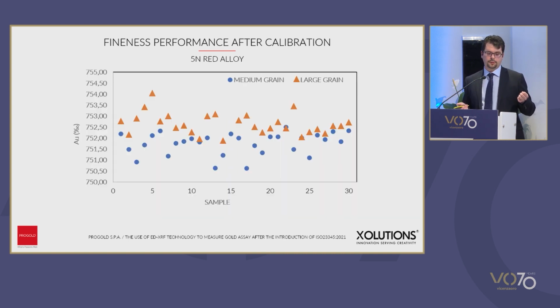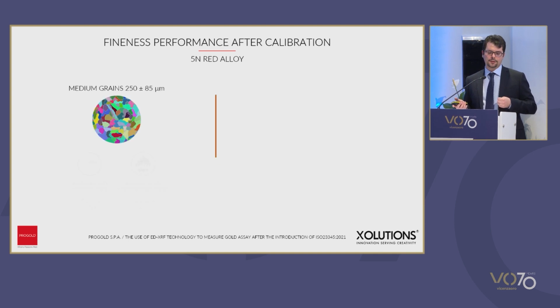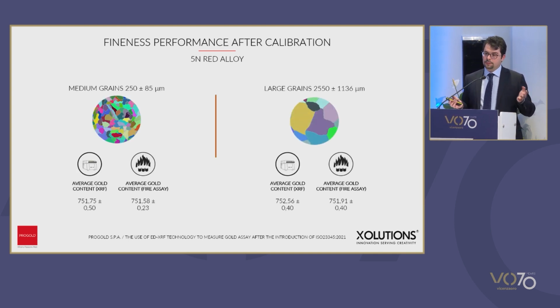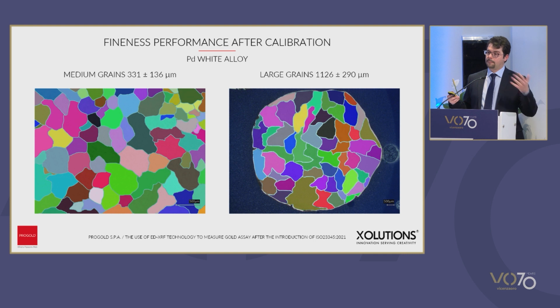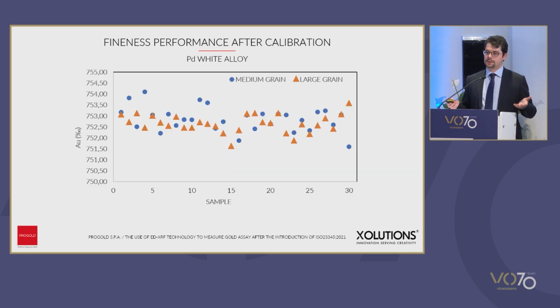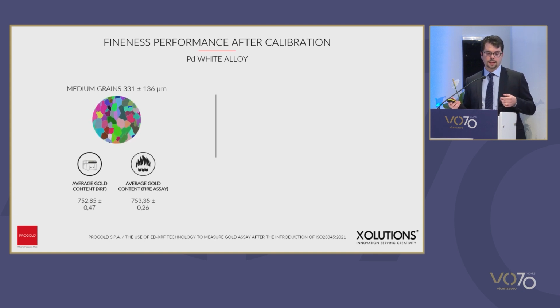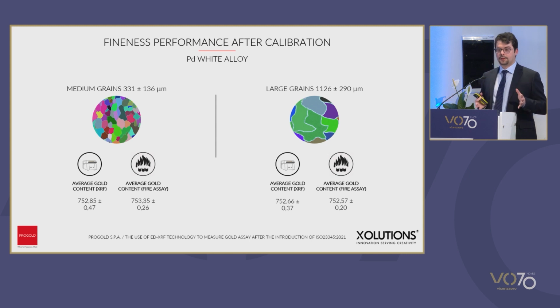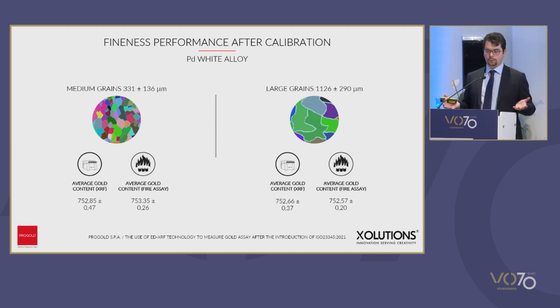Now, if we look at the same set of analyses for red gold, these are the results. A compatibility of the results between fire assay and X-rays, and some comparable mistakes, and in both cases below half mm. Again, we see the values, and after making our tests again, this is what we achieve. So, correspondence between X-ray analysis and fire assay within the limits of measurement errors.